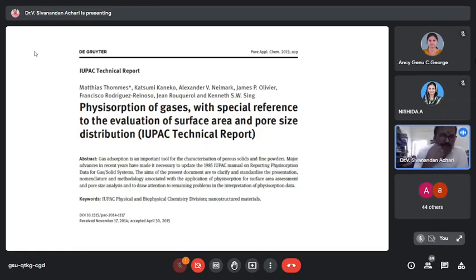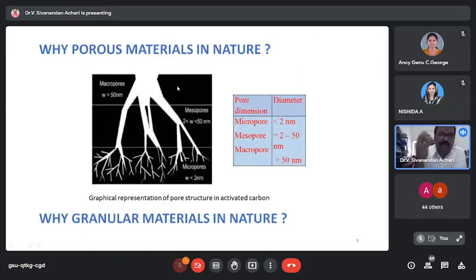He made a lot of permutations on the BET isotherm, and found that the BET isotherm can be extendable up to the relative pressure P by P0 equal to 0.35. That is a very significant contribution of Kaneko. Brunauer and Emmett assumed that if you take a porous material, when you apply a relative pressure starting from 0.05 to 0.3, most of the porosity will be saturated, and the linearity is maintained up to a relative pressure of 0.3. This is the invention and the technical significance placed by Brunauer and Emmett through a series of analyses. But Kaneko analyzed those data and later found that the BET equation is valid beyond P by P0 equal to 0.3. Up to 0.35, most porous materials maintain the validity of the BET equation.